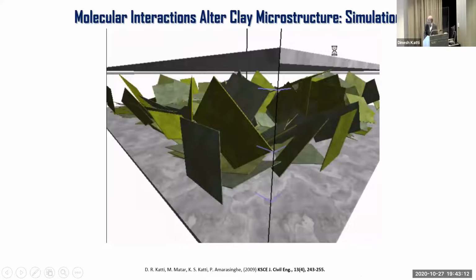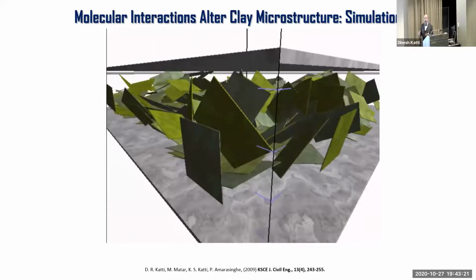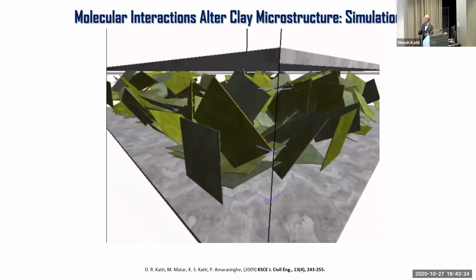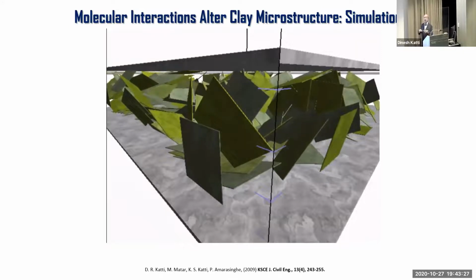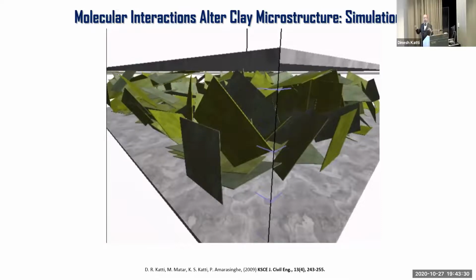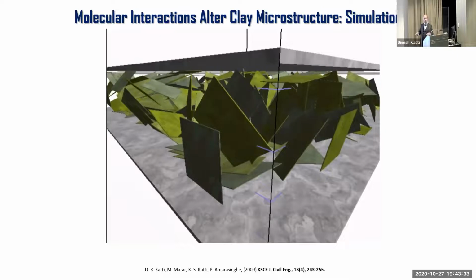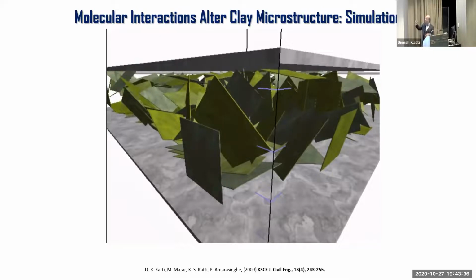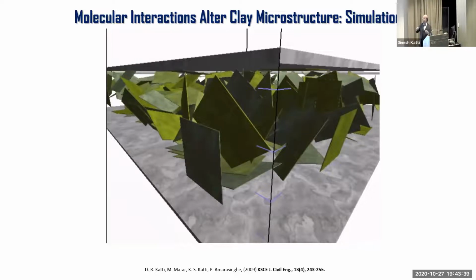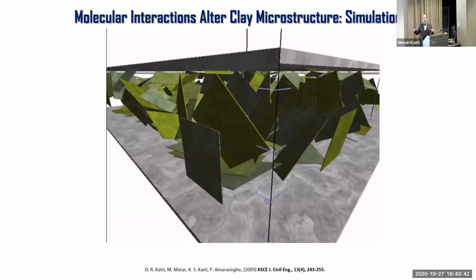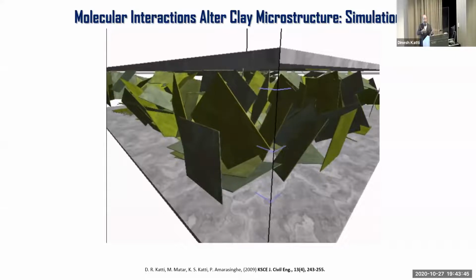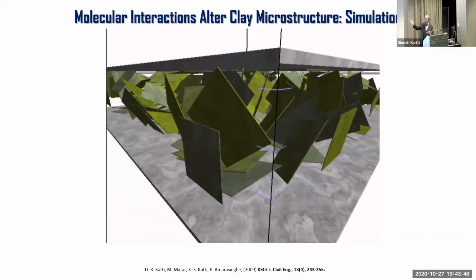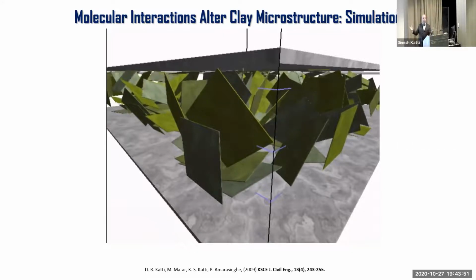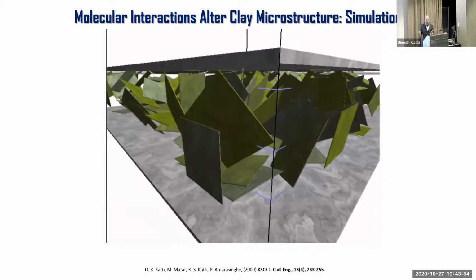So now we also did discrete element modeling simulations, and you can see those void spaces being filled up by broken particles. So the particles which are broken down, they fill up the void space and basically seal off the clay and prevent water and other high polar fluids from flowing through, creating a perfect barrier. So because of molecular interactions, particles break down and fill up these void spaces and seal off the clay. But non-polar fluids which do not have very strong molecular interactions with clay do not break down the particles and do not create this perfect seal. Okay.